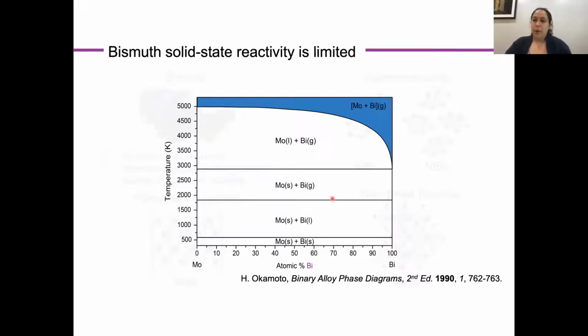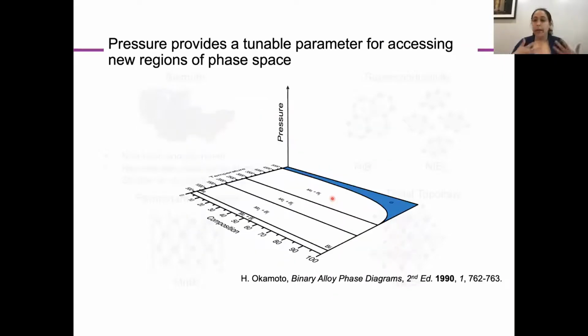And so the answer to this problem might be somewhat obvious given the topic of the seminar series, but in our group, we like to use pressure as a tunable synthetic parameter for accessing new regions of phase space. And as Steve mentioned, I started doing high pressure research for my postdoc position. And I was tempted at first to think of it as mainly a densifying force. But in fact, at geologically relevant pressures, you start to see that the chemistry of the elements is changed significantly, such that in high pressure phase space, you start to get reactivity and structures that sort of defy our intuition based on ambient conditions.